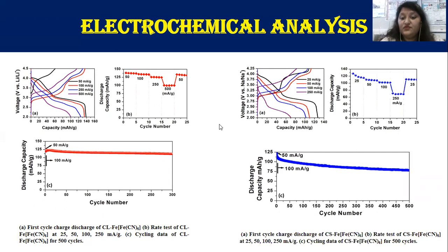And the second figure shows the sodiated PBA rate study, and the cycling performance was also studied. The charge discharge profile is depicted in A, which shows a good initial charge capacity of 110 mAh per gram at 25 mA per gram, whereas in the case of lithium it was only 61 mAh per gram. So further from the rate test, it is concluded that the sodiated PBA is a good cathode for sodium-ion battery application. The rate performance has been conducted from 25 to 250 specific currents, and the discharge capacity